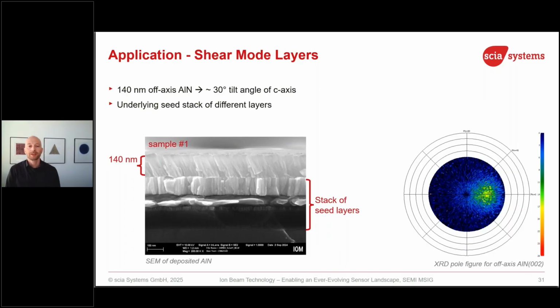How does this look in reality now? We did a 140 nanometer AlN layer with about 30-degree tilt, which is a very nice angle to get a good shear mode here. On this picture, we see this tilted crystal structure for the aluminum nitride, and then some other layers underneath, like electrode and some other seed layers, in order to make sure that we get this nice crystal orientation.